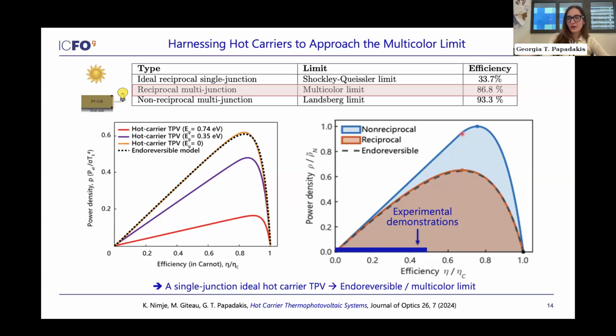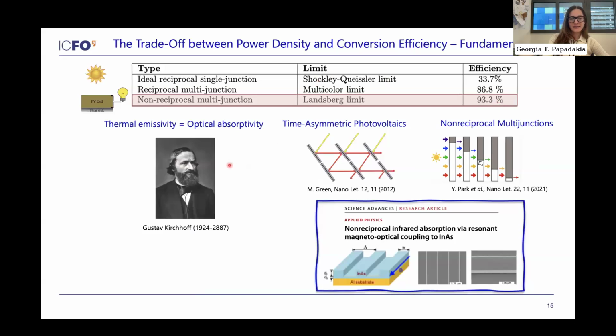Now let's look at this blue curve here. This blue curve corresponds to non-reciprocal PV cells and TPV cells. As you can see here, in the case of solar PVs, if I could allow non-reciprocal cells, I would get to 93% efficiency, which is gigantic. So what do I mean by that? If I could break Kirchhoff's law, which dictates that the thermal emissivity is equal to the absorptivity of a material, I could create PV cell configurations that look like this.